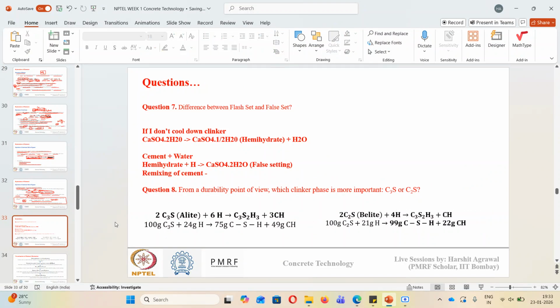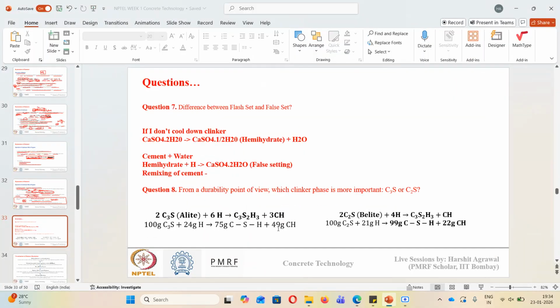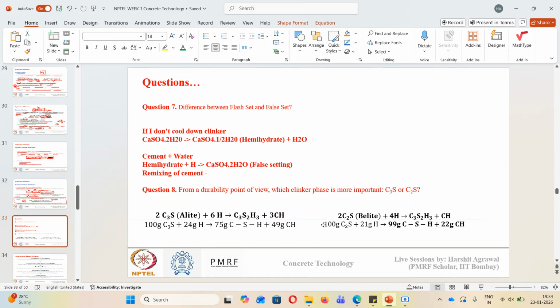Okay. So if you remember, we talked about two hydration products, CSH and CH. Which of them is undesirable to us? CH or CSH? Okay, CH is undesirable to us. So if there is more formation of CH, then there is more chance that later on CH will give rise to durability issues. So for clinker phase, from durability point of view, C2S is more important because it produces less CH content per 100 grams of C2S. You can see, compared to C3S, almost half CH is produced due to C2S for the same amount of phase. Okay, so that's why I say from durability point of view, C2S is more important.